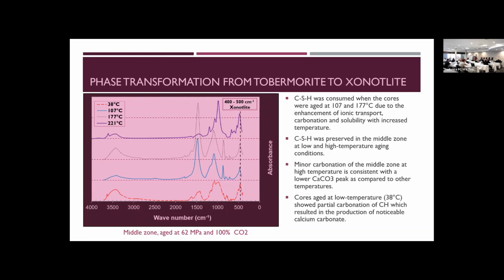Furthermore, the cores which were aged at low temperature, like 38 degrees C, show just a partial carbonation of the CH phase, where we noticed a little more calcium carbonate in the form. So you will notice here that 38 degrees C is on the lower end for our system. And this is probably interesting from the chemical point of view of the cement carbonation process as such.